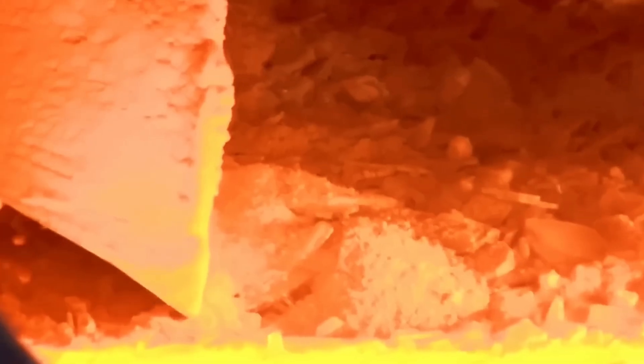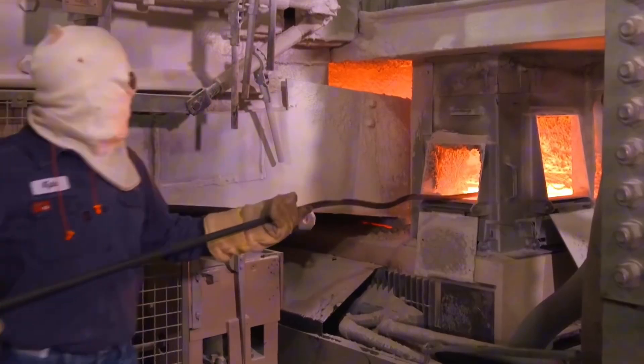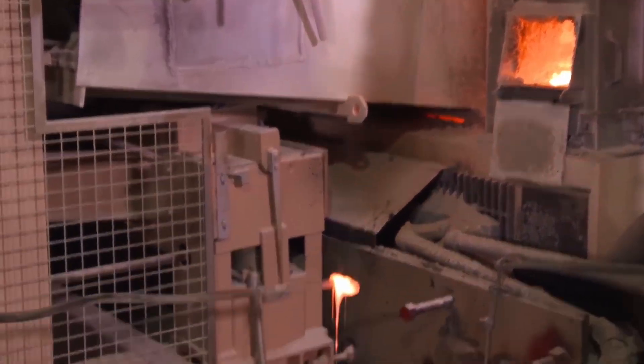The molten, gas-enriched glass flows into a long tunnel furnace at 900-1,000 degrees Celsius. The reaction begins: glass swells and expands, turning into a lightweight porous mass. Before your eyes, the dense molten ribbon grows several times in volume. Thousands of microscopic bubbles fill the material, forming a structure similar to pumice stone.